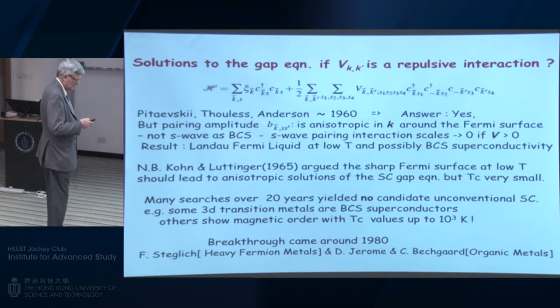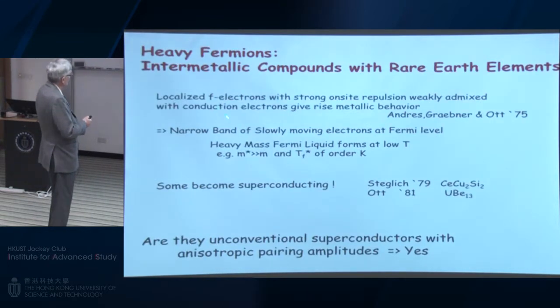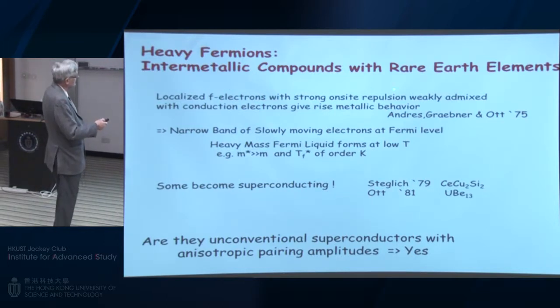Jerome and Bechgaard discovered organic materials which form metals. The heavy fermion metals are intermetallic compounds with rare earth elements. Now, the rare earth elements have localized, partially filled F-electron shells. So the F-electrons are concentrated near the nuclei. So there's a strong repulsive interaction since they have strongly localized wave functions. But the heavy fermions occur through the weak admixture with the conduction sp electrons, which are much more mobile outside these ion cores. And this class of material was discovered around 1975.